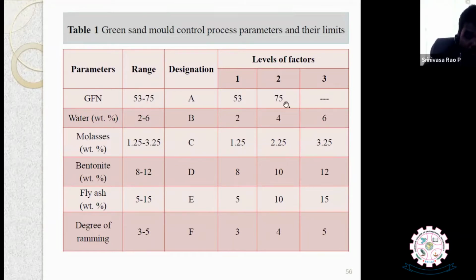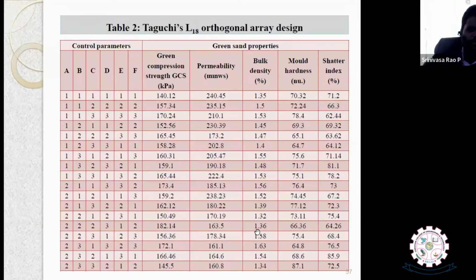Grain fineness number, the level is 53. We calculated the grain fineness number with sieve analysis of the sand. Then the water quantity, how much to be added, and molasses, the percentage by weight to be added, and bentonite, fly ash, and degree of ramming. While making the sample, the degree of ramming is how many rams we use to make the sand sample. So that is the degree of ramming.